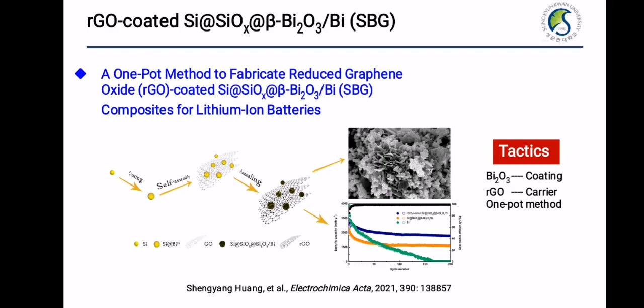So in this case, I use the one-pot method to fabricate silicon@silicon oxide@beta bismuth oxide@bismuth anodes. We can call them SBG composites. Through this schema, we can see that the SBG anodes were synthesized in 3 steps. First, the bismuth ion intermediate was in situ coated over the silicon by the solvothermal method. Secondly, the silicon@bismuth ion was loaded on 2D graphene oxide to build 3D composites.